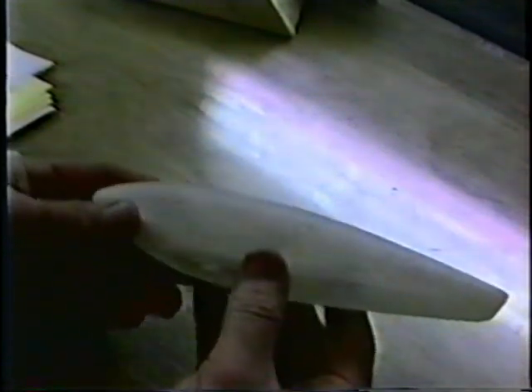They come from Australia. But what I would say to do with these, if you made a fiberglass cowling or wheel pants or whatever, any fiberglass material, you want to sand it with maybe 320 or 400. After you're done sanding it, get a nice finish on it. You want to put at least two or three coats of auto primer on, sand it again, let it dry overnight. Then the next step would be, obviously, you want to wind up somewhere down the road with, let's say this airplane is going to be white. This is a coat of acrylic white on here. Let that dry overnight. Sand that maybe with 600.